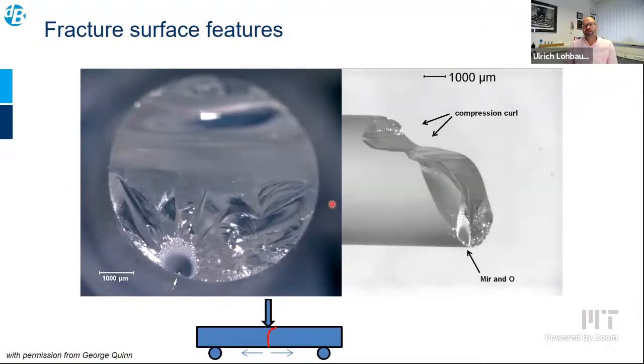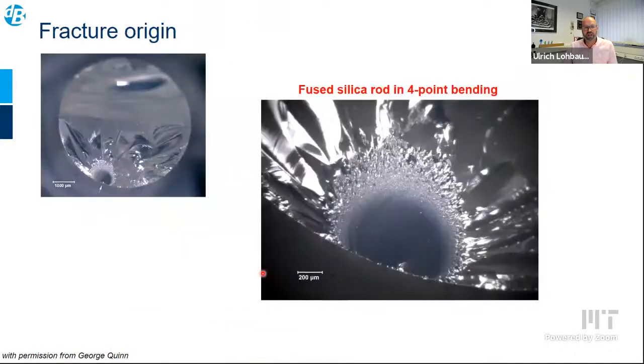This is a glass rod, but it has such a nice fracture origin that I have to show you this example. This is a glass rod that is fractured in 4-point bending, and you can very easily see the fracture origin at the bottom side, where the highest tensile stress is and where it should be located. So this is again the same fracture origin, and we can see or identify it.